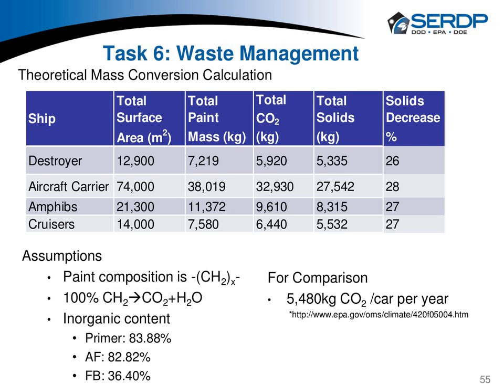Okay, with the remaining time I've got, I want to get into the waste and the integration. Another theoretical calculation we did was to identify how much of the paint would be converted into solid left over from the inorganic fillers, and how much would be converted to gases, in particular CO2, under the assumption that we have 100% conversion of the paint to CO2 and water, with some assumptions about the filler content. When we ran this calculation and compared it to how much CO2 is produced by one automobile in a year to remove the paint from an entire ship, it's really insignificant overall when you think about the amount of gas. And in this case, for the amount of solids, we're taking the original mass and reducing it 26%, so we have a decrease in the solids.